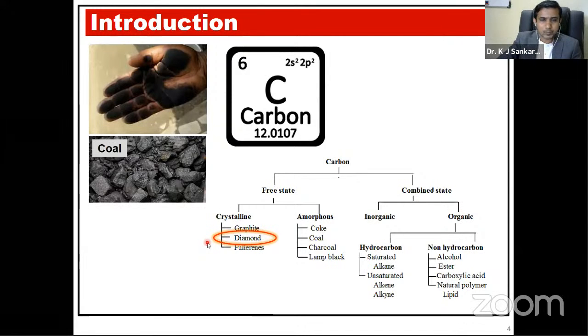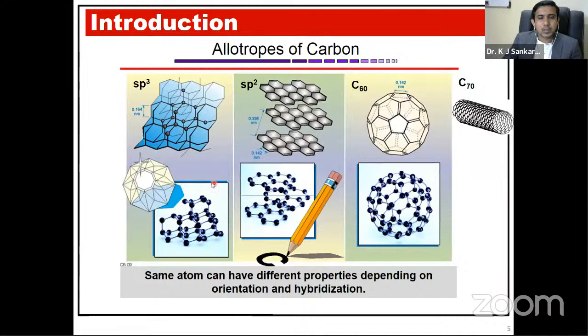for the microplasma applications. So as you can see here, these are the allotropes of carbon, like sp3, which is for diamond with a bond length of 0.154 nanometer, and you can see this is sp2, this is graphite with a spacing of 0.142 nanometer, and this is bonding with the hexagonal, which is bonding with van der Waals bonding, and this is C60 fullerene balls and C70, and carbon nanotubes or something like tube-like structures. But we can get more allotropes of carbon. So there is only one same atom, the same carbon atom, which has different properties based on the different hybridization. That depends on the orientation and the hybridization. So a carbon material can vary in properties depending on the orientation and the hybridization of that carbon material.